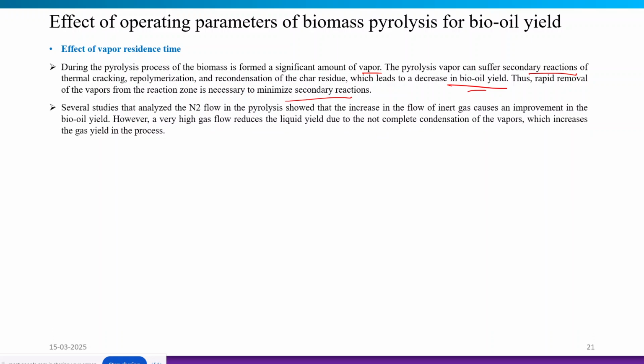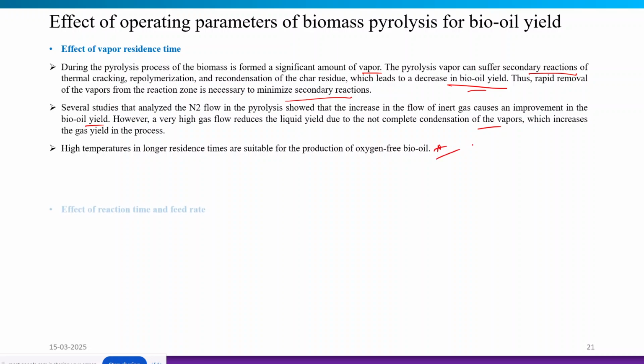Several studies analyzed that increasing the flow of inert nitrogen gas inside the reactor causes an improvement in the bio-oil yield. However, if we increase the flow rate of the inert gas too much, the liquid yield will reduce, because the condensation of the vapor will not be completed, which ultimately increases the gaseous yield in the process. Higher temperature and a longer residence time are suitable for oxygen free bio oil production.